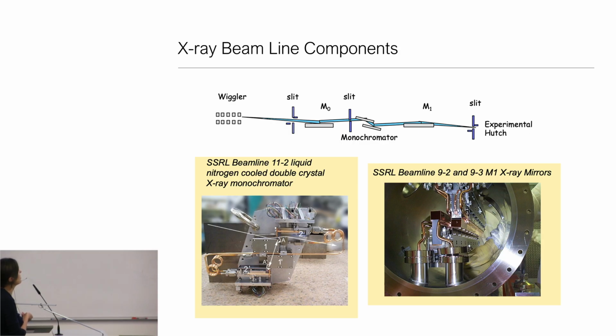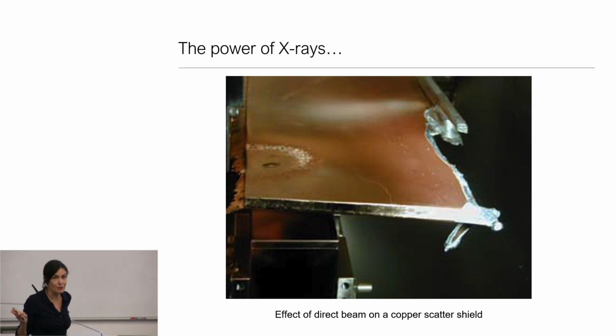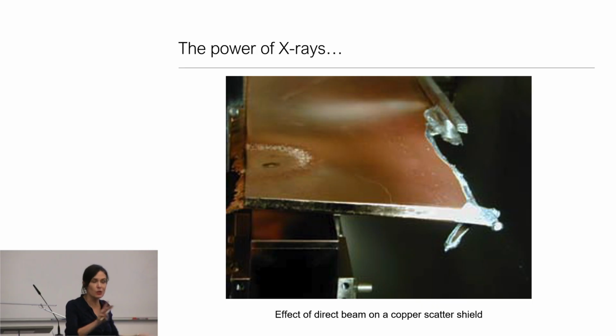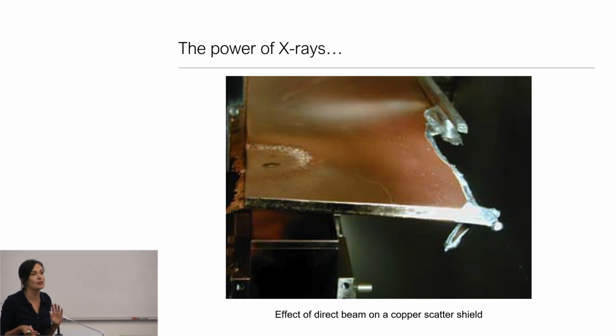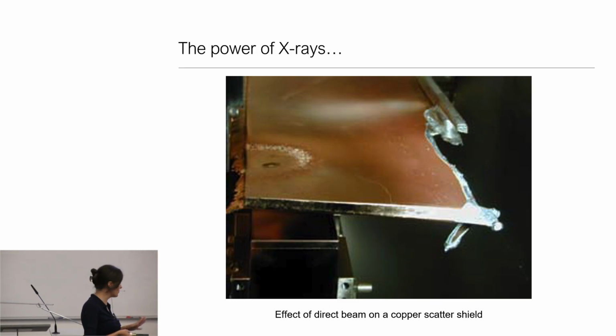Or they even need to be cooled by liquid nitrogen. This is just an example of a monochromator that's being cooled by liquid nitrogen to keep the crystal itself from being instantly distorted. And just to emphasize the power of the X-rays generated by these synchrotron facilities, this is a picture from when I was a beamline scientist at SSRL during the commissioning of a beamline. So it wasn't open to users, there were no safety violations, but limits hadn't been set on where you could steer the beam. And so the engineers had actually steered into a piece of copper shielding just for a moment. But this is a rather thick piece of copper shielding that instantly melted with the energy of the beam.